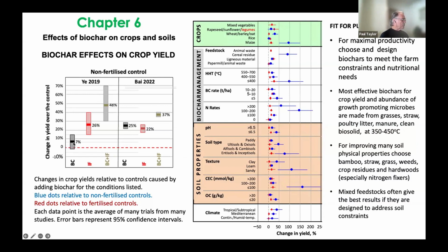And you can see that if we look at all the biochars of all types in all climate zones, in this study, we get about a 7% increase over a range, of course, but average 7% compared to the non-fertilized control, and fertilized compared to the non-fertilized control is about 26%. In another study done 3 years later, they found about equal effect of biochar and fertilizer. So it gives you a sense of the variation in these meta-studies, but probably some of this difference is because we're learning to make better biochars and applying them more carefully. So they're working better. In both cases, though, the studies found that biochar and fertilizer combined worked better than either one separately.